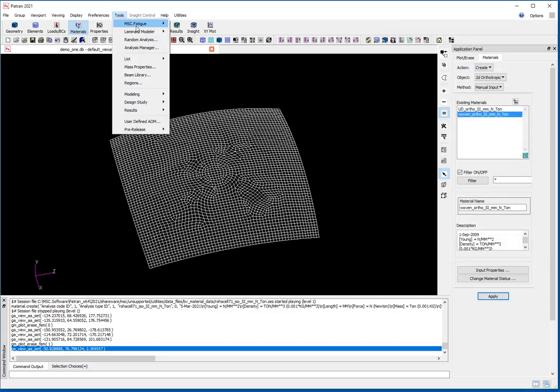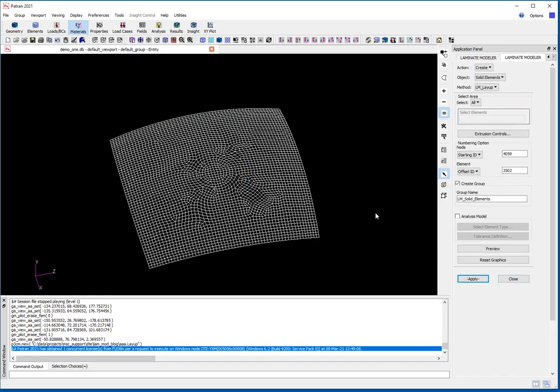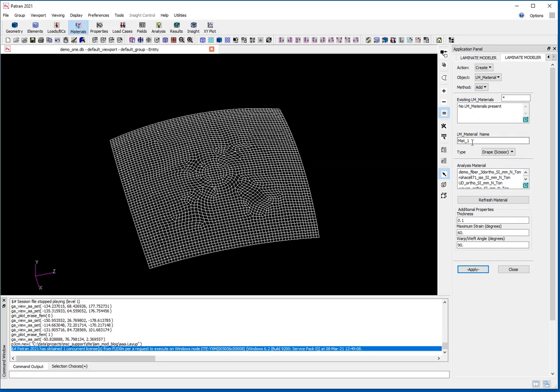Laminate Modeler lives up in the tools menu. I'm going to make a new layout file and give it an arbitrary name. The first thing I need to do is create my LM materials. The first one is the UD, which uses a slide type draping. I'm going to set the nominal thickness — the thickness of the prepreg — at 0.1 millimetres.